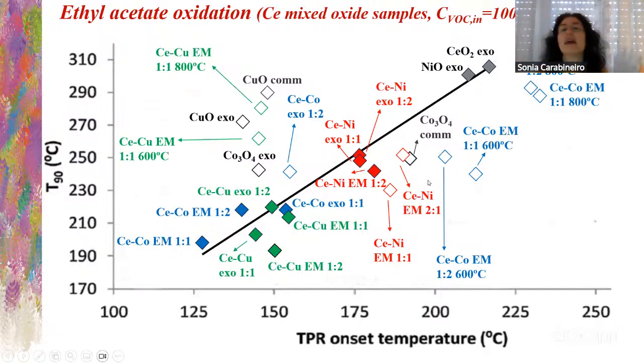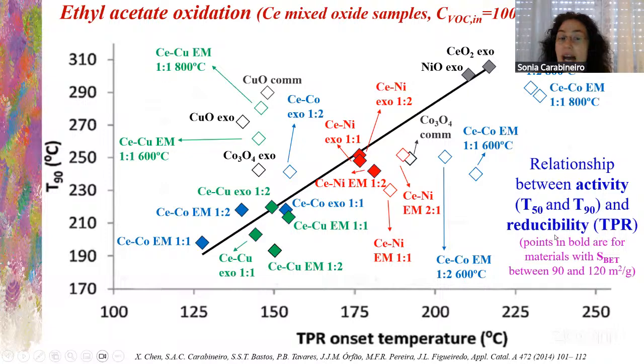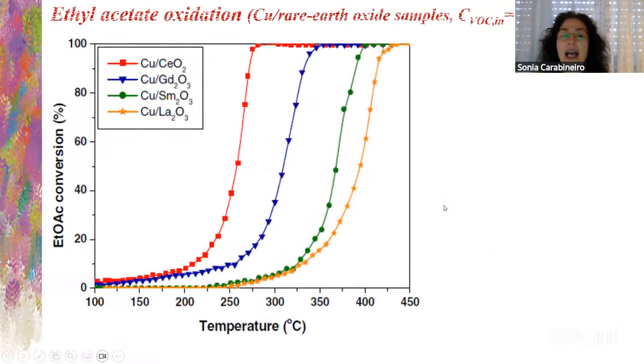So we saw this is a very broad dispersion. But if you see the points in bold, these are for materials that have a higher BET surface area. So with these ones, we can say there is some relationship between the activity and the reducibility. So it's not just reducibility, the surface area is also important here, because the others are more or less flat.